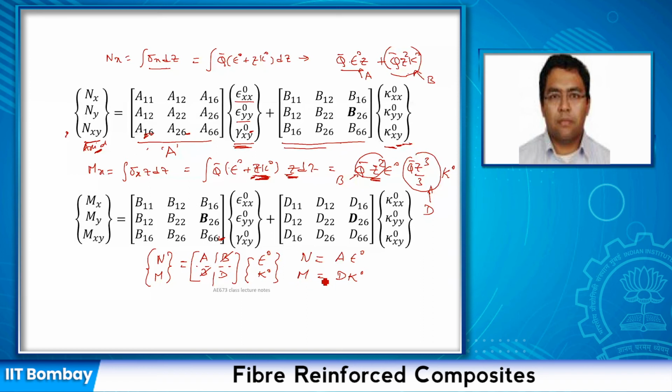So, as a composite laminate designer, we have to know how to eliminate the coupling when it is required, how to keep the coupling when it is required, and the other couplings which are also important are the in-plane warpage curvature, the D26 and the D16 terms. These are also very important values, because they connect the in-plane moment, the MXY, the warping moment, to the curvatures and the strains.